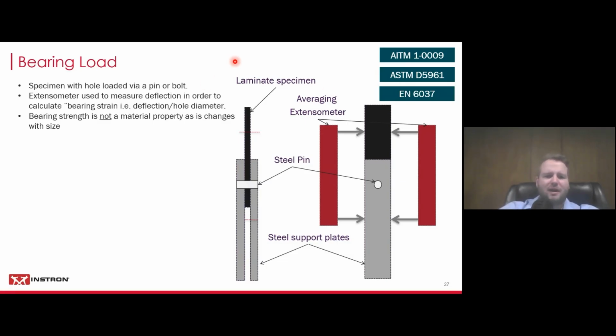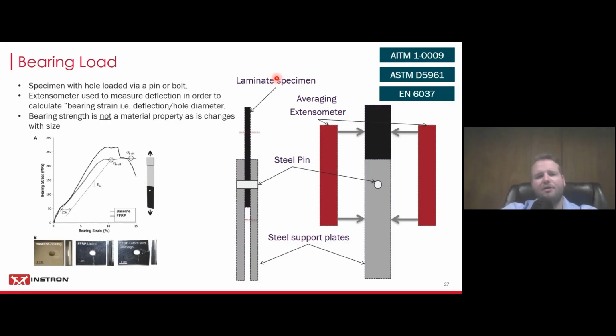The specimens have a hole, and then you have a pin or a bolt with which you're loading it. So you put that into that hole that you initiated in your specimen. And then you apply averaging extensometers on both sides. And it's important to understand here that bearing strength is not a material property, as it changes with the size. So the size of the hole does change your bearing properties.